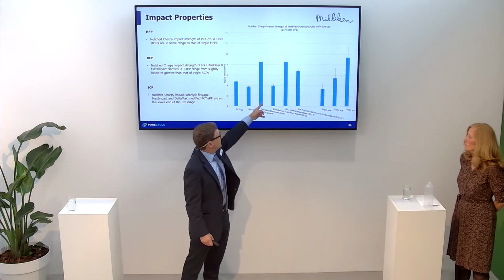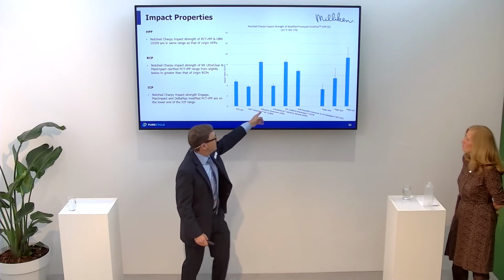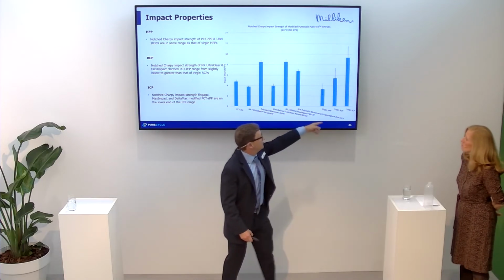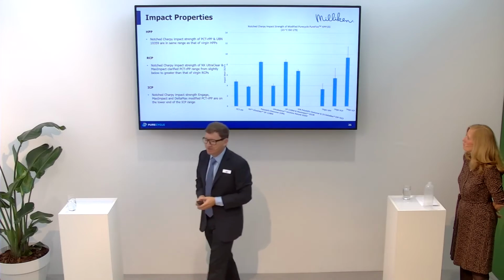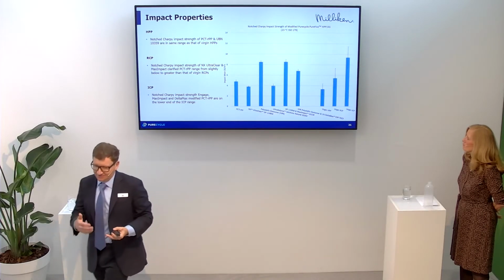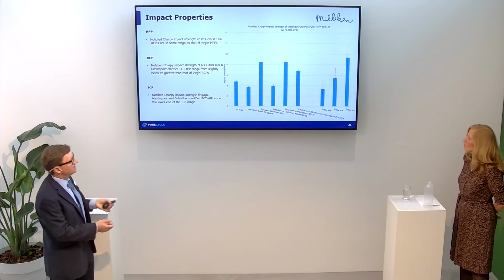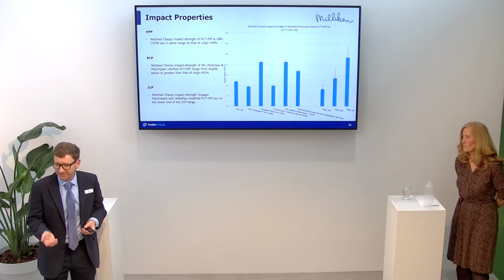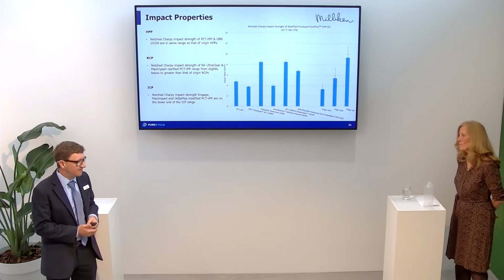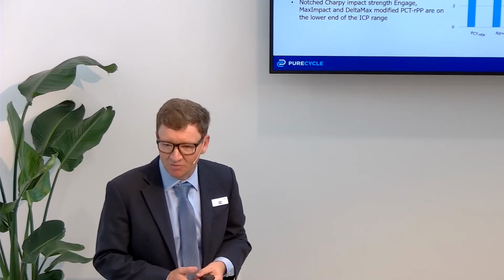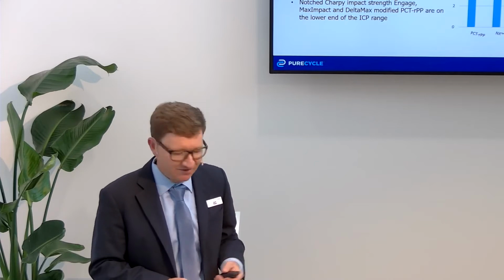When we start adding the elastomers, both just the base elastomer and the Delta Max, you can see again we're in that virgin ICP range. So there's a little bit of a detriment, I guess, to adding the impact materials because you're not at 100% recycled content anymore, but you need to reach the mechanical properties in the performance space to make a product.